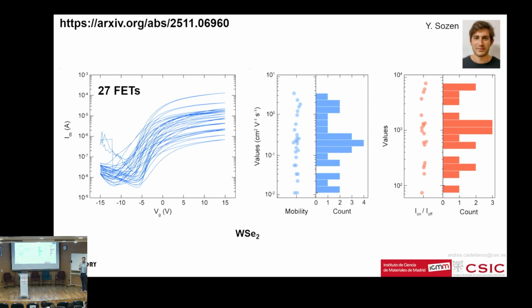In this case, field effect transistor characterization takes way longer than the photodetectors. So we were limited to 27 devices, because it takes quite some time to do the gate traces, the IV curves, the transfer characteristics, and so on, okay? And when plotting mobilities and the on-off ratios, you see this huge dispersion, and it looks like, well, forget about this fabrication method.